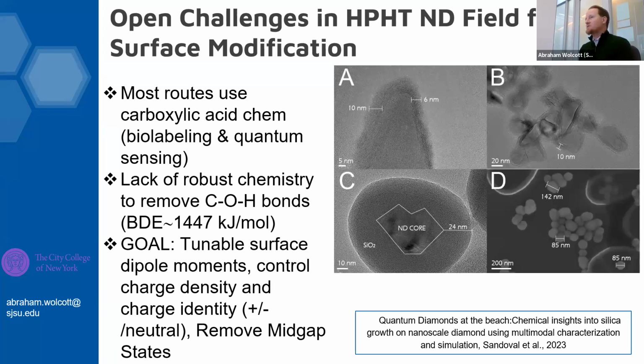Most routes use carboxylic acid chemistry for biolabeling and some of these quantum sensing applications. But I want to make the argument that HPHT, under specific conditions, mostly has alcohols. And these alcohols have a large bond dissociation energy, so they don't want to change very readily. And one of the grand goals of the lab is to tune these surface dipole moments, which then affect our NV photophysics. Can we control the charge density on the surface? Can we control the charge identity from positive to negative to neutral species? And more importantly, can we remove mid-gap states that cause decoherence of our NV centers?